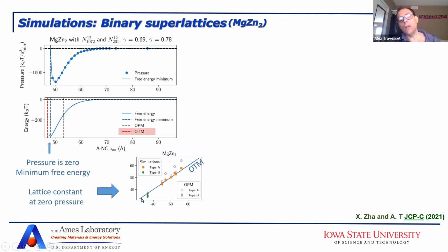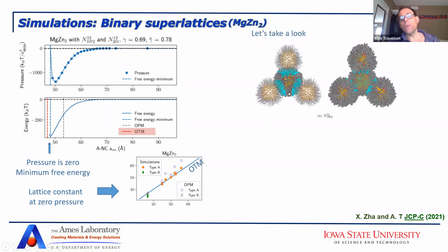And then here you have it for magnesium zinc 2, which is the lattice I've been using to illustrate the point. You see here, this is type A, the ones that have formed vertices, how well they are described with the OTM model, while the hard spheres are quite a lot off. If we take a look at the actual simulation, we can see what this looks like. This is the diamond structure of the large A particles that form magnesium zinc 2, and you can see here the presence of the vertices.